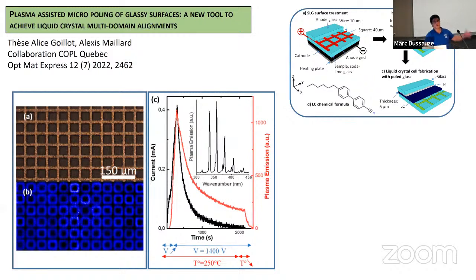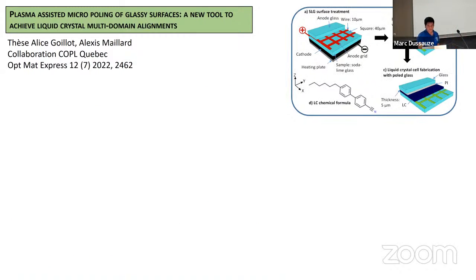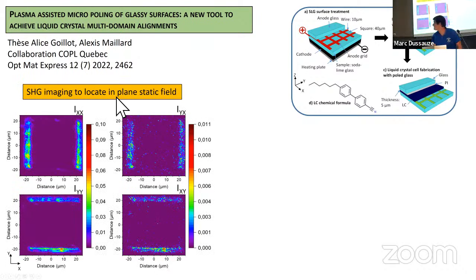So that's much more controlled than what I have shown you before. And then we can look at the surface of the glass. We can look at the response by second harmonic generation in order to locate the fields that could be implemented inside the glass. And you can see that the fields are located at the edges of the grid, okay, and they are very polarized. So if the grid is parallel to the y-axis, the field is perpendicular, and that's very uniaxial also, like I have shown you before.